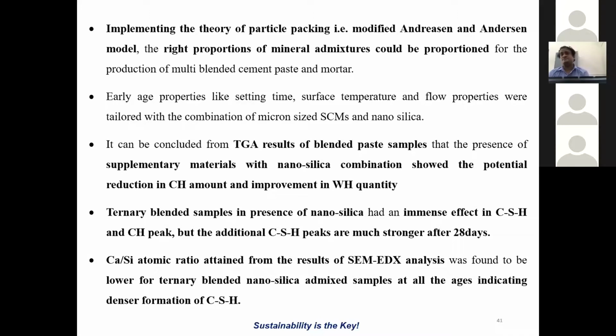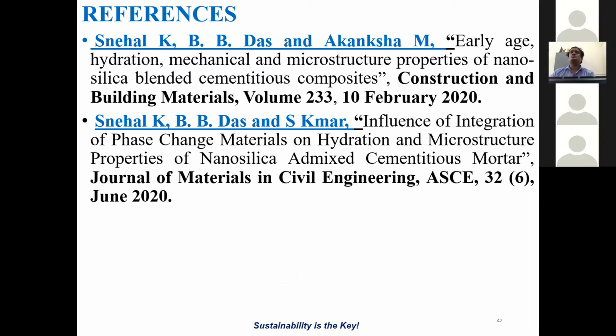So that is the way the nanosilica integration, even on a small scale, in a small percentage, while keeping the secondary cementitious material at a large percentage, makes my cementitious composite more sustainable as well as high performance, because I see the formation of hydration products. So that is the way I can conclude that I am able to produce a sustainable cementitious composite by integrating secondary cementitious materials as well as nanosilica.